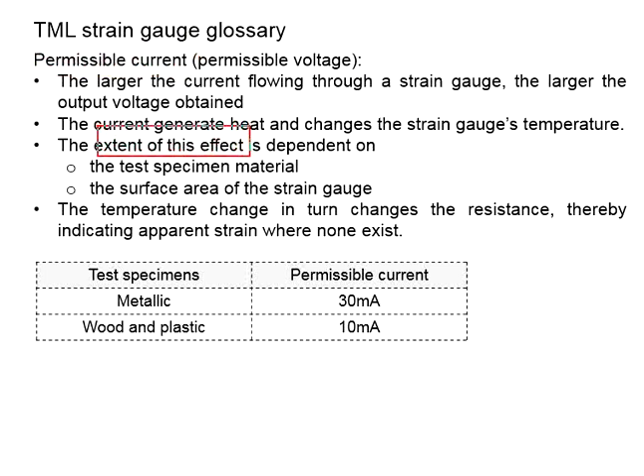It was said that the extent of these effects is governed by the type of material of your test specimen. With that, the permissible current changes accordingly. For metallic materials, the permissible current will be 30 mA. As for wood and plastic, the permissible current will be 10 mA. I believe the difference is due to the ability of the test specimen to disperse the heat. If the heat can be quickly dispersed, faster than the accumulation of temperature caused by the current, then a higher permissible current is allowed. Otherwise, the current will have to remain low. I believe this is the reason.